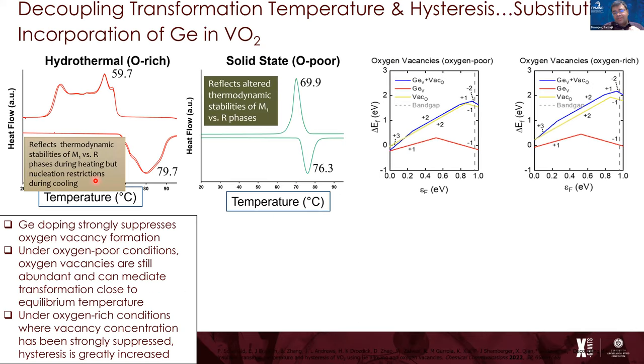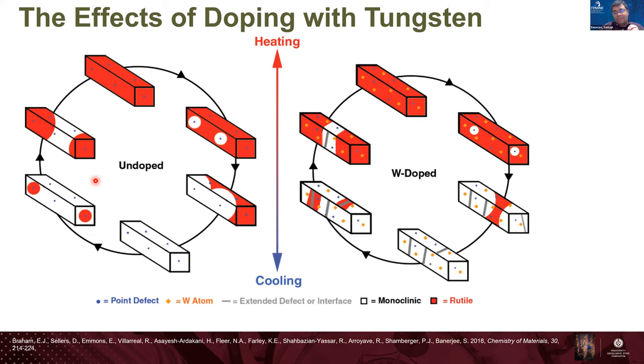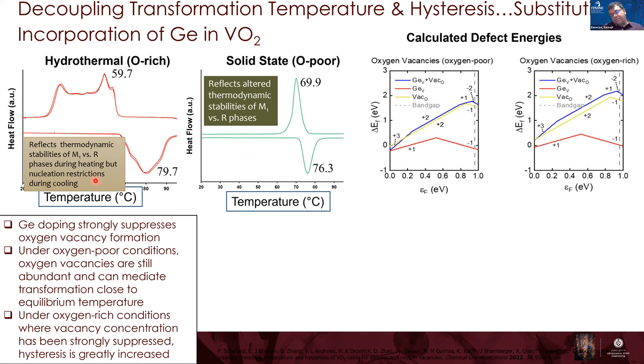Now, tungsten is great. This is a great model system, but it's the wrong way. We want to push this transformation temperature up so that we can get to temperatures more common to data centers and such. And so we worked on germanium, which pushes the transformation temperature quite high. We can go a little bit higher than this too, but close to about 85, 90 degrees. And so again, this is a beautiful example of where you can push the equilibrium transformation temperature up.